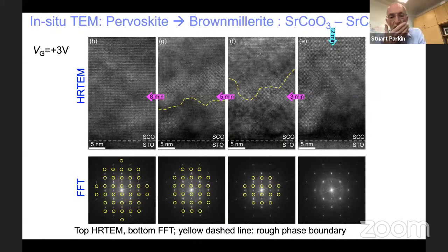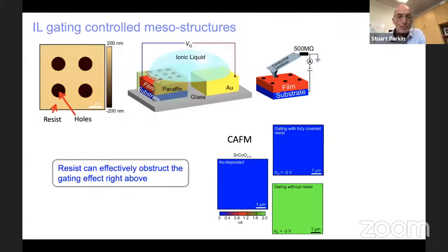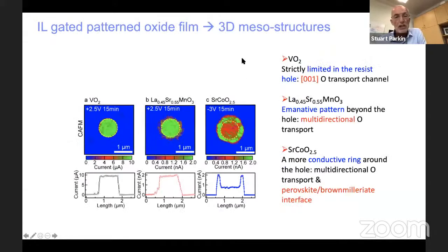So what does that mean? Why is this interesting? I think it's interesting because we could use this to create magnetic mesostructures. So what we do now is we take an oxide layer like the strontium cobalt oxide SrCoO2.5, and we put a resist layer on the top, and then we make holes in the resist and we liquid gate through the resist, and we then only change the brownmillerite to the perovskite in the holes. So we create metallic holes in the middle of an insulating layer, shown here by conducting atomic force microscopy after we've gated the device and removed the resist layer.